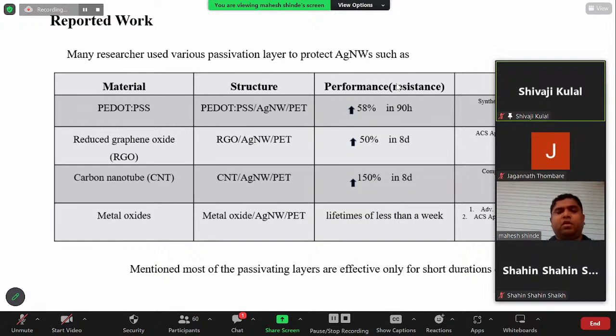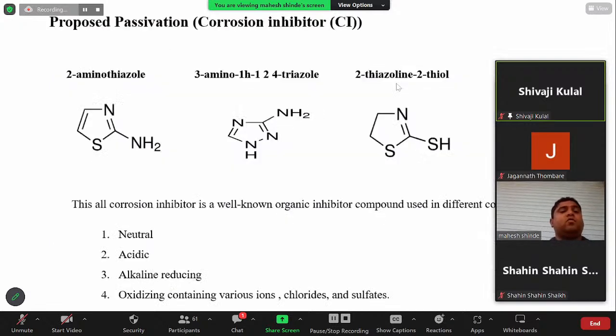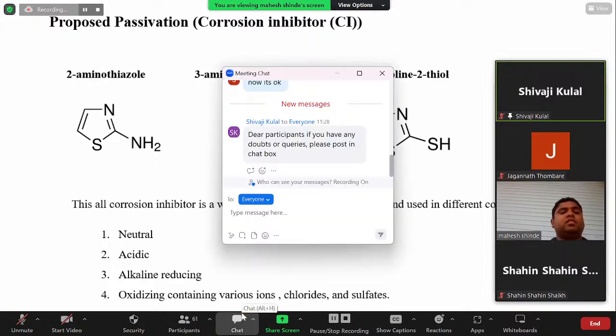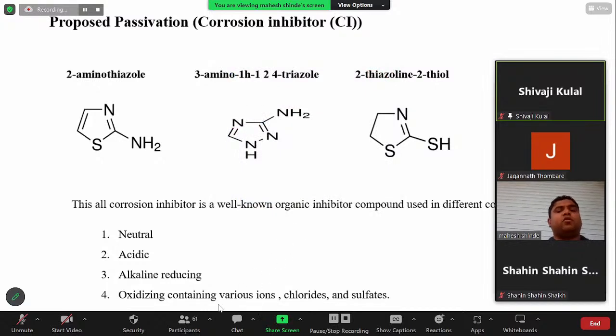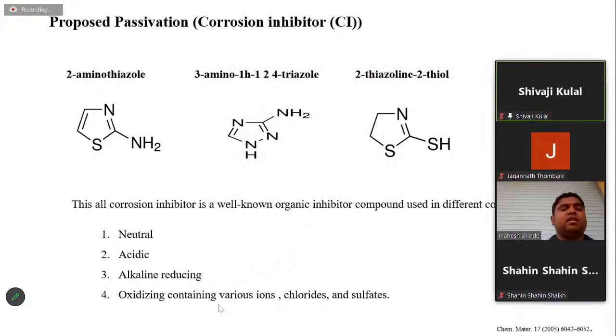For that, my proposed passivation layer was different chemicals which are well-known corrosion inhibitors, like 2-aminothiazole and benzotriazole. These are well-known corrosion inhibitors, and they provide protection in different media, such as neutral, acidic, alkaline, and oxidizing agents. So I used these corrosion inhibitors for the protection of silver nanowire.